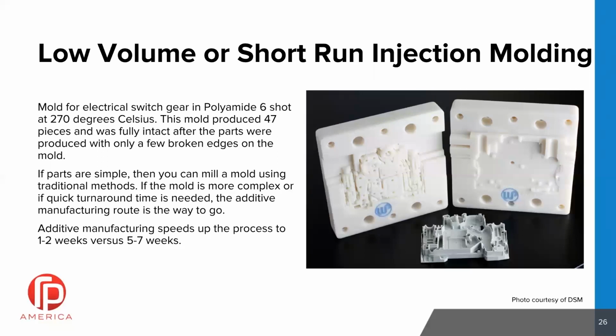If the parts are simple, you can still do a mill or a mold that can make sense. But if the part gets more complex, then additive is definitely a way to go. And this material provides opportunity to do that. You think about the additive manufacturing can speed up the process 1 to 2 weeks compared to 5 to 7 weeks. You could run through multiple iterations in this process before you'd ever get your first mold that was cut. So we actually are dealing with a couple of customers right now that are very highly interested in this. We've done some examples where they were injecting a Velox material that had a melt over 500 degrees, and we were using these mold inserts, and they performed flawlessly.